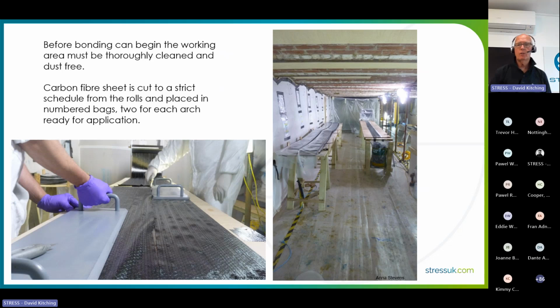But then we came down to the cutting. So everything's prepared, everything's ready to go, and we now need to make these sheets exactly the right size. You can now get carbon fiber sheet in rolls of different widths. In those days, it only came in 500mm wide rolls, and we needed 200. So in fact, each one was cut, but very easy. You're running along the lines of it. But a good pair of shears will actually cut through carbon fiber in any direction.